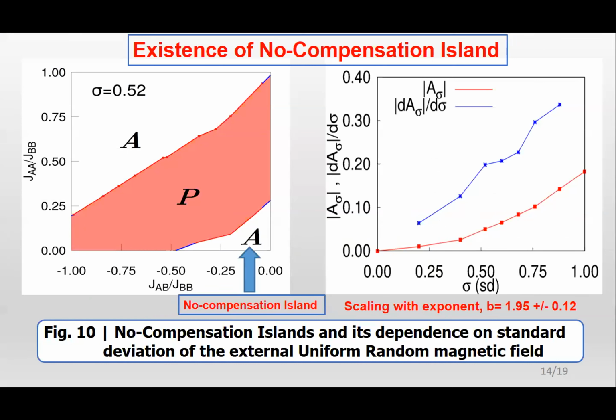The conclusion is included in the slide. As we increase the standard deviation of the field, we see that in the phase diagram the area of the no compensation islands actually increases, and the nature of increment is basically a superlinear one.